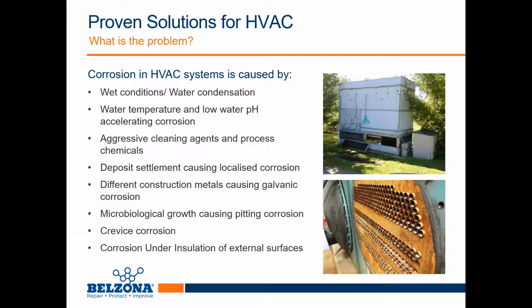Water pH: the pH in untreated water drops. Corrosion tends to increase. The lower pH also dissolves various oxides and exposes more of the metal surface to corrosion. Aggressive cleaning agents are used to clean these types of systems. The water treatment chemicals used to prevent scale and fouling accelerate corrosion rates. They lead to perforations, holes, and severe metal loss on units and services.